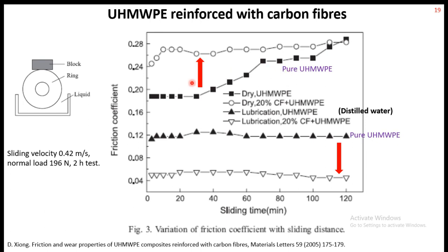For dry condition, the composite gave slightly higher coefficient of friction, but for the lubricated case, comparing pure UHMWPE and the carbon fiber composite, there is a drastic reduction in the coefficient of friction. So having carbon fiber in the UHMWPE matrix has helped in the lubricated case. Again, these experiments were done with distilled water lubrication, so we need to also check how the results will show if we use bovine serum as the lubricant.